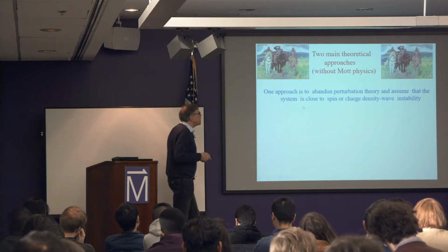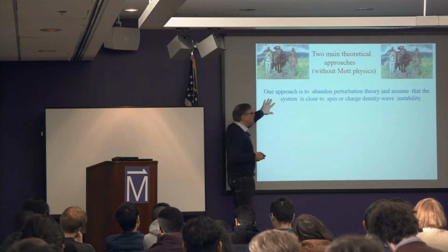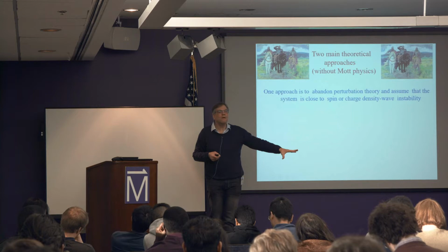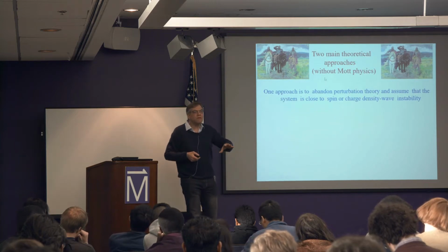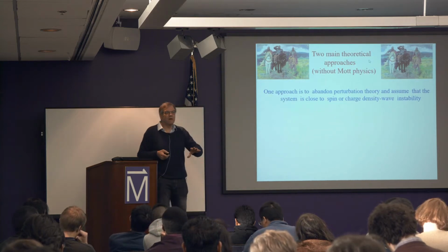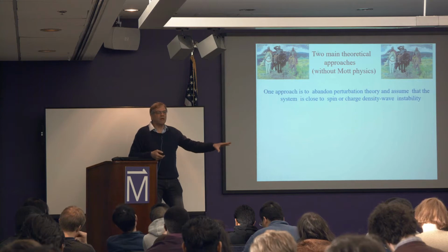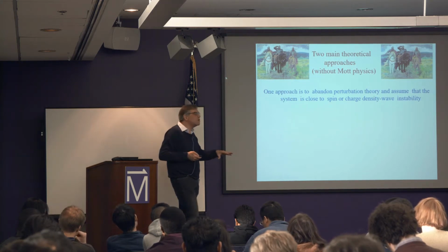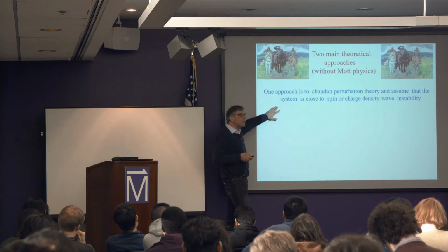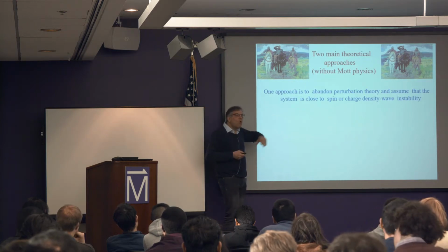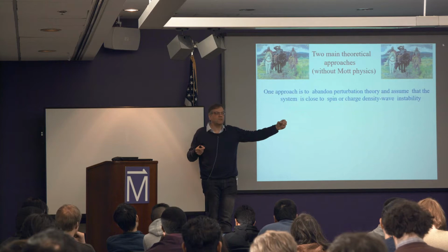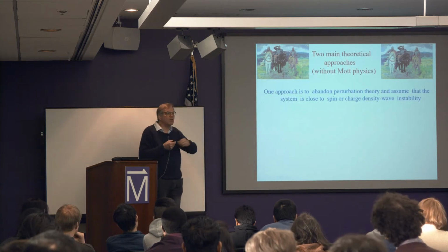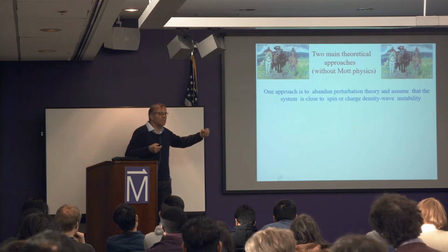This is basically the approach that says, okay, let's look at the phase diagram of all these materials, and notice that in most cases, another ordered state is nearby, most likely magnetism. Then you can say, let's consider a system close to magnetic instability, when almost certainly the interaction with large momentum transfer is enhanced simply by virtue of being close to an instability with large momentum.